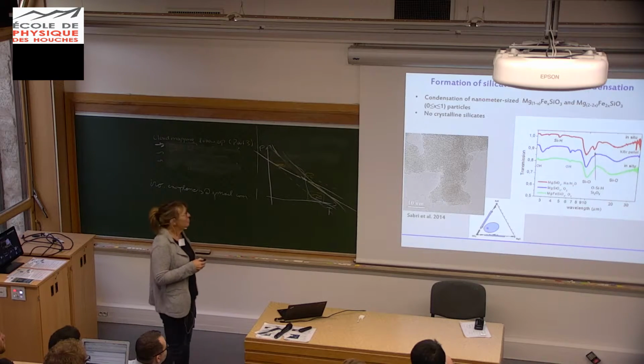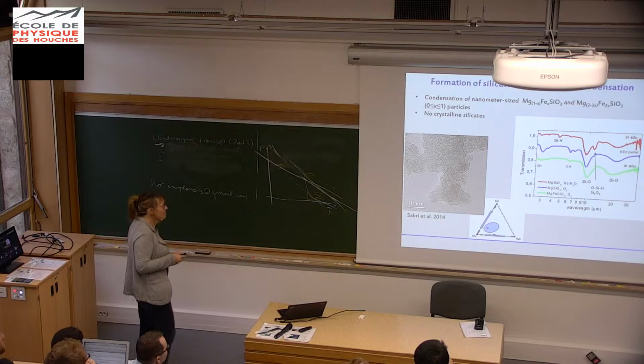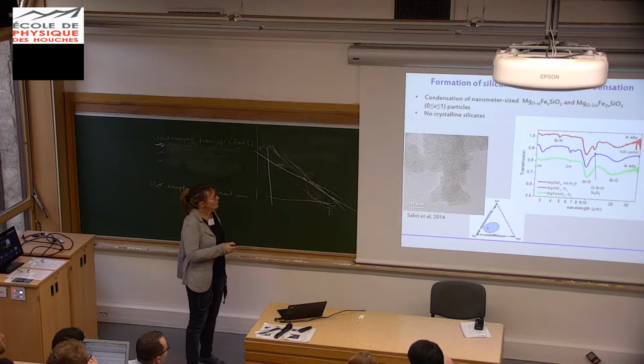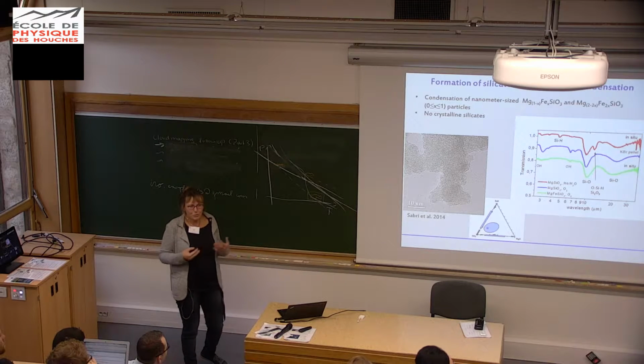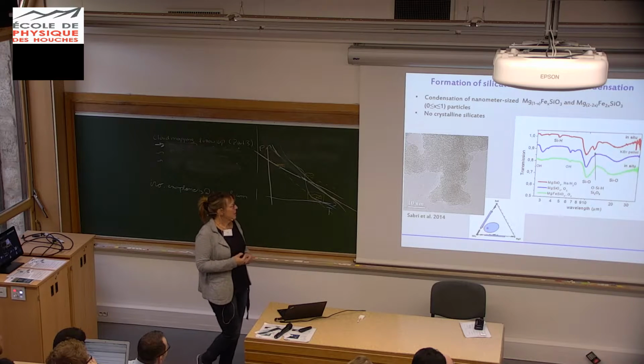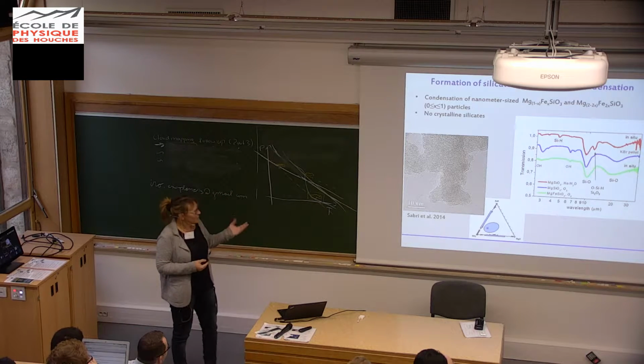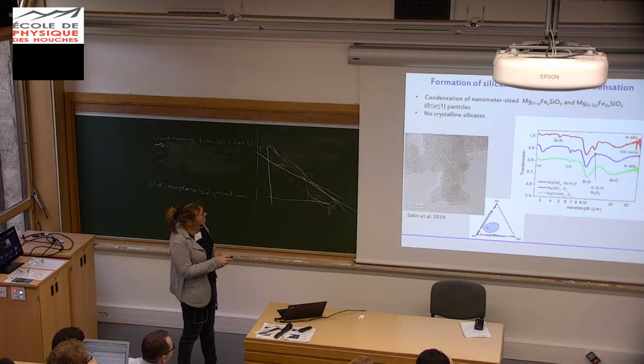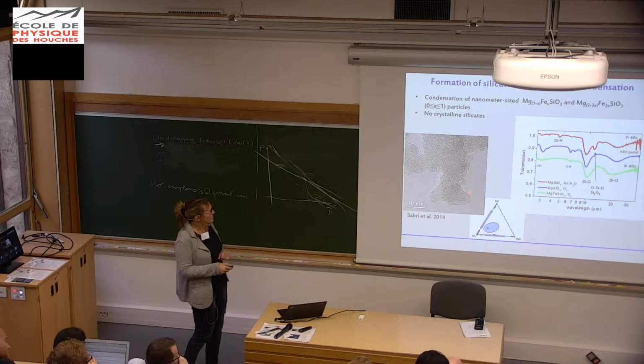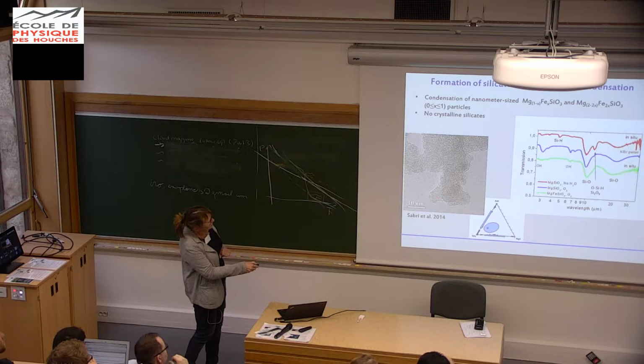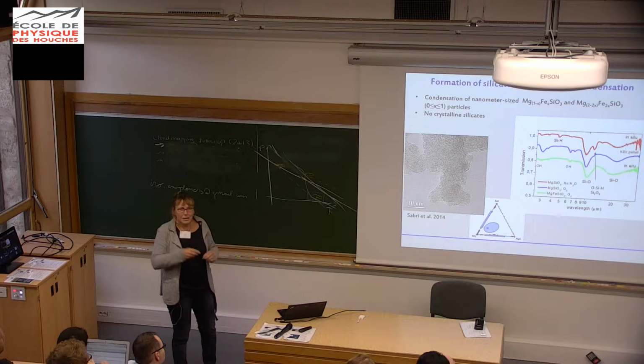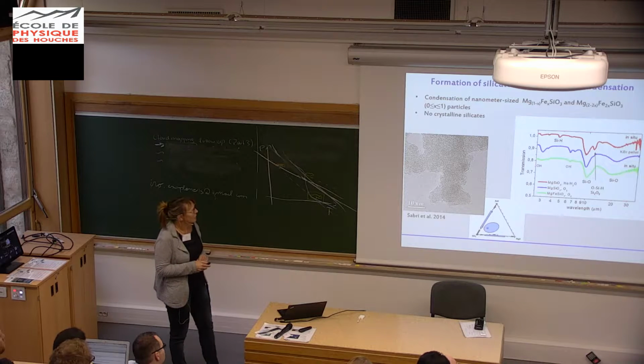So what did we produce when we studied the condensation of silicates? First I have to say we never produced crystalline silicates, never ever. If you produce these silicates by homogeneous nucleation, you really start with something amorphous. You can see here, this is a high resolution electron microscope image showing the primary particles - they already started to condense together. It's a little difficult to see, but here you can see it. They form agglomerates and fluffy structures of the dust grains.